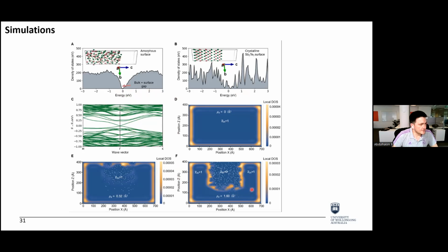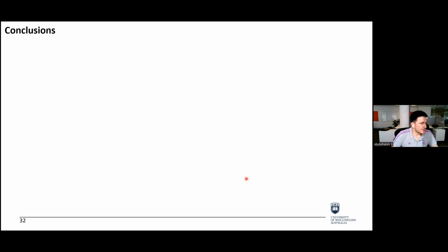And this is a real space Hamiltonian model done by some of our collaborators from RMIT, and it clearly shows that when this crystalline material is not amorphized, without any disorder, it clearly shows surface states at the surfaces between the crystal and the vacuum boundary. As we gradually increase the disorder strength or induce amorphization, these surface states gradually disappear, and eventually under much stronger disorder strength, it wraps around the boundary between amorphous and crystalline region. That's really interesting.